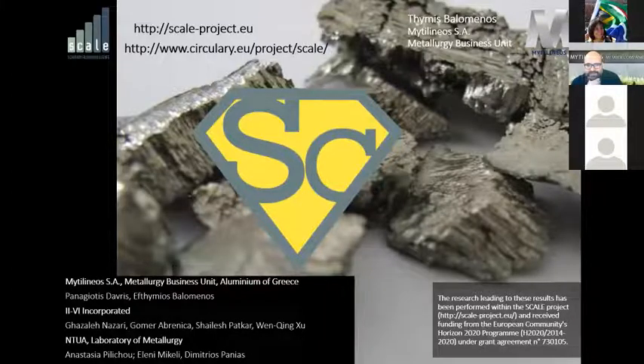So this means that you need to make the rest of the cost from the value that you will get out from the slag. Now, it is questionable if by leaching the slag, again with sulfuric acid, for example, you will get such great results. I mean, we know that we can get 100% scandium extraction with leaching the slag at about 3 molar acid. But again, we just get 20-something parts per million scandium in the pregnant liquor solution. No iron, which is a huge benefit in terms of this resin problem. But still, we're just around 20. It's not like we get to 100.